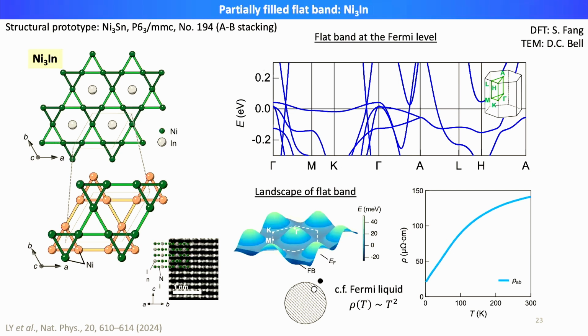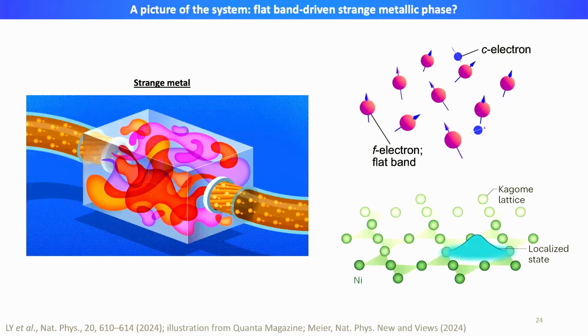So the observation that we have a strong deviation from this Fermi liquid behavior in our system, when the flat band is put near the Fermi level, is indicating that very likely these quasi-particles are no longer well defined as in the Fermi liquid case. So this T-linear behavior is often called non-Fermi liquid or strange metal, depending on who you talk to.